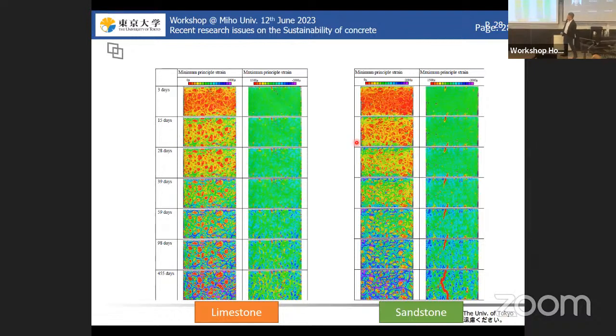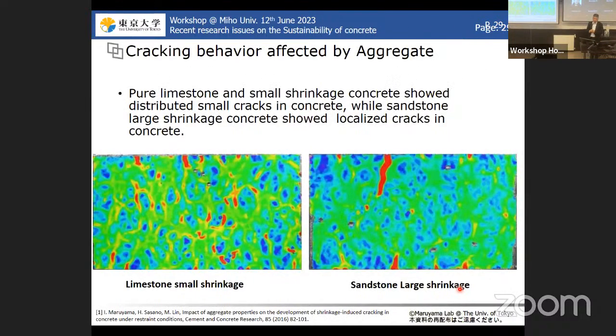This is the minimal principal strain distribution, and this one is the maximum principal strain distribution. And you find that in the limestone, the shrinkage cracks happen on the surface, but they do not develop inside. In the case of the sandstone aggregate, it develops and goes inside, something like this. So if we close up the picture,